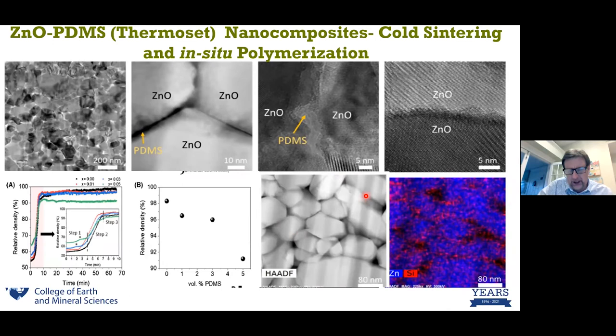So just to prove to you that these must be low temperatures, you can see here the densified microstructure, the sort of classic 120 degree angles between densified ceramics. But when you look more closely in the TEM, in this particular case, there's a polymer around each grain boundary. In this case, a silicone elastomer, only up to about 5 volume percent in this particular case, but still maintaining densities above 96%. And you can see from the densification that this all happens within 10 minutes, right? Typically, just sintering zinc oxide takes multiple hours, right? This is happening within 10 minutes and densifying the materials, but leaving a polymer also in the grain boundary. So you can have it free of polymer or with various different volume fractions of polymer and different chemistries of polymer, all making up these types of composites.